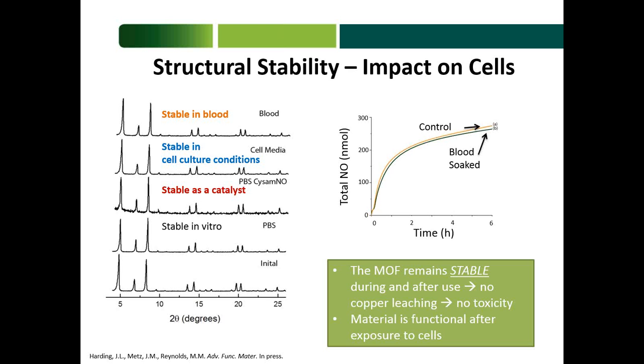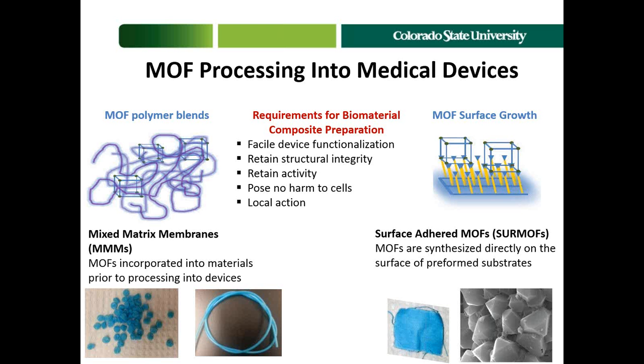if we degrade any of the materials, then they have the potential to cause toxicity effects. The materials on the left show that even under cell culture conditions in blood and so forth, they remain intact, so we don't leach any toxic metals out, and their catalytic function remains similar both before and after. So the material is functional even after exposure to cells, and the cells do not seem to respond negatively to the material. We then put these into different medical device platforms. Extruded tubing is what I'm showing you on the left, and a coating grown off of the surface through a simple manufacturing washing process is on the right. And these materials are highly functional without showing any leaching or toxicity to cells using a variety of ISO standard models.